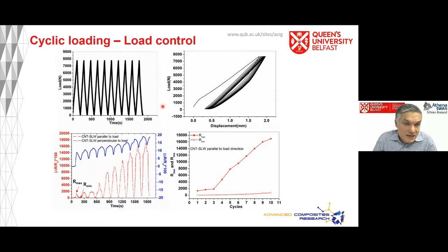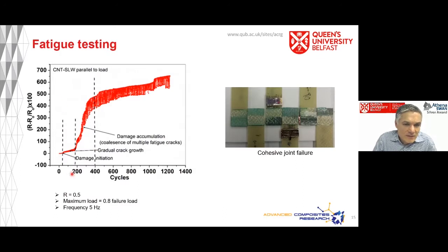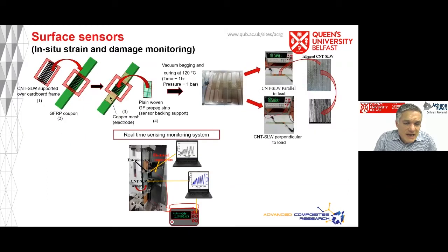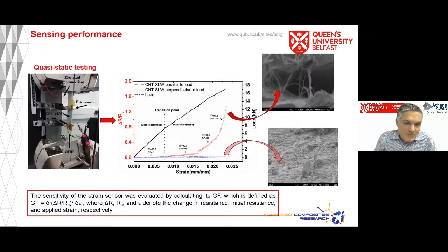And of course, we've looked at different cycling rates. I won't go into any details here. You can see for fatigue testing, we can also capture the response quite well. We have mounted these as surface sensors, more like a strain gauge. And what we did there was to get the carbon nanotube web and again put it between thin glass fiber pre-preg strips and then attach that to the specimen. And what you can see is again that we can measure a change in resistance.